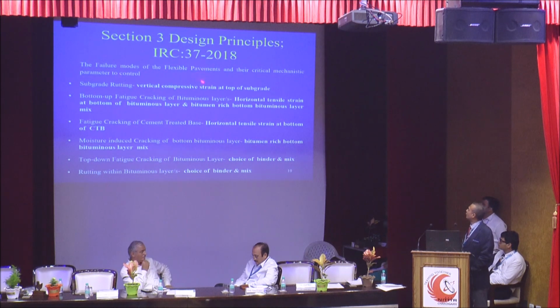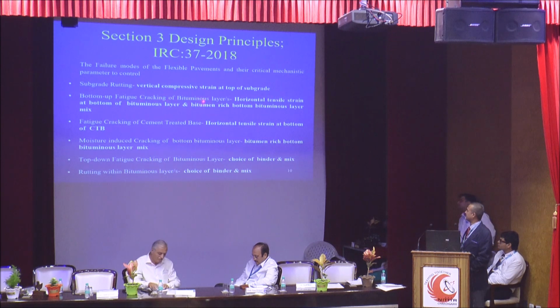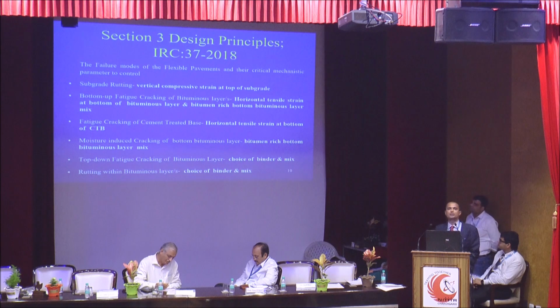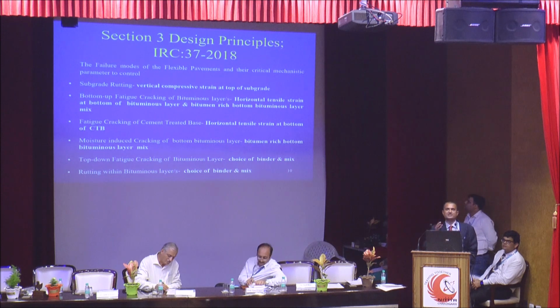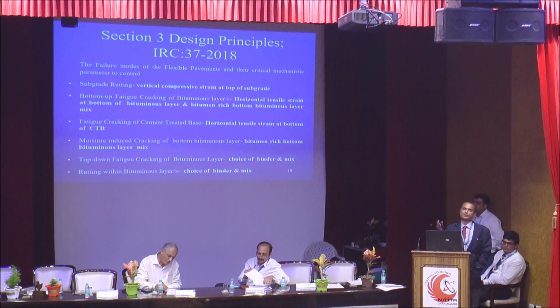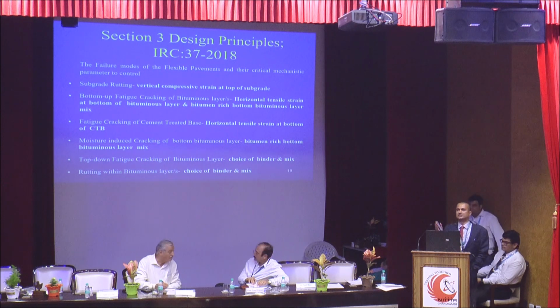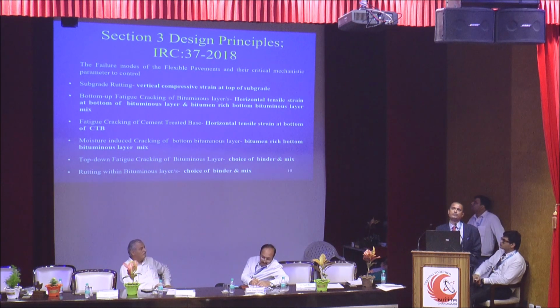The failure modes of flexible pavement and their critical mechanistic parameters: subgrade rutting is controlled by vertical compressive strain at top of subgrade; then bottom-up fatigue cracking of the bituminous layer. Dear friends, this bottom-up fatigue cracking distress mode is only applicable for pavement with thin bituminous surfacing. I have never seen a pavement designed with IRC 37 2001 onwards having this type of failure, that means bottom-up fatigue cracking, until and unless there is great subsidence and consolidation.